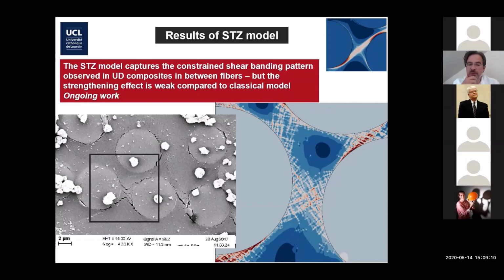Yes, in the present system, the RTM6 system, it fails in tension after about 5% deformation macroscopically. Of course, this has to do with the defects I mentioned at the end, but in smaller volumes the deformation you can reach before damage is much bigger. For instance, what you see here is some damage in the composite, but this is after 30-40% deformation. So even some region might be in tension and not fail yet, because you don't see starting defects, or you will get the decohesion probably before.